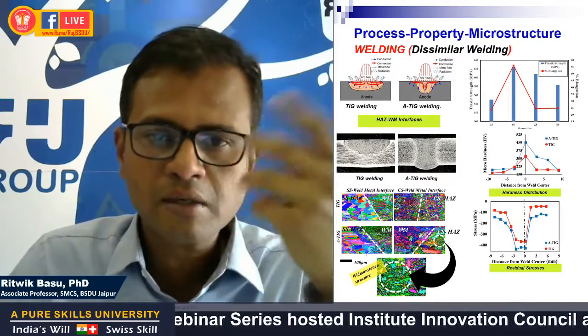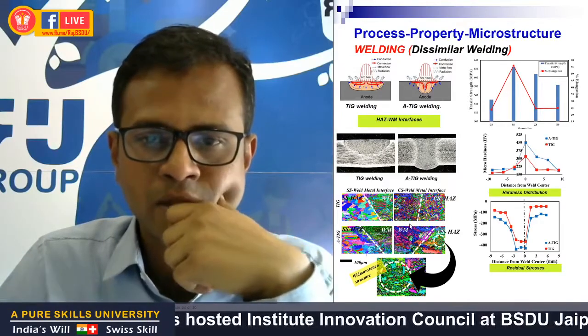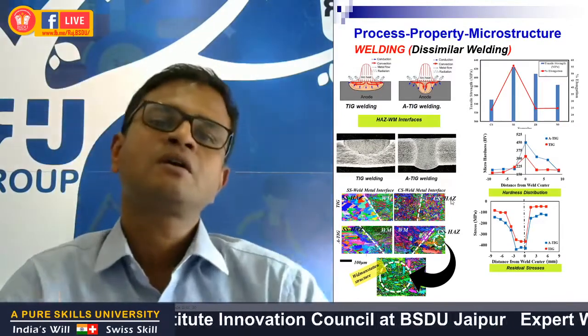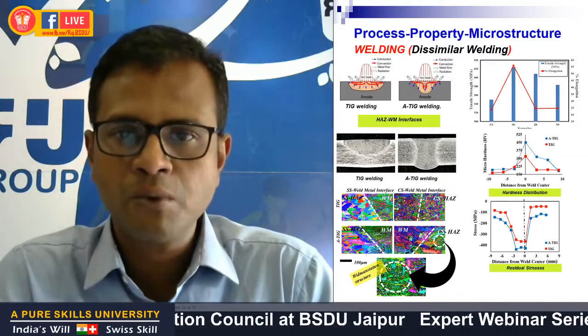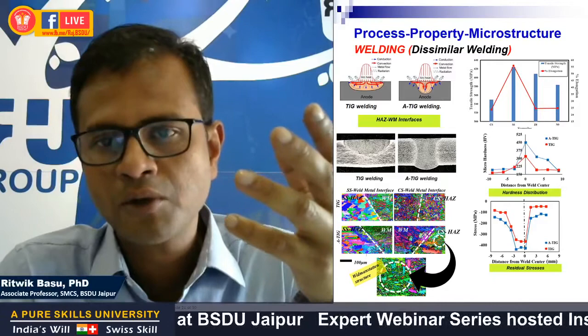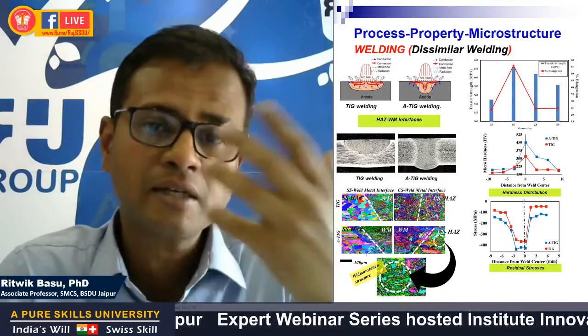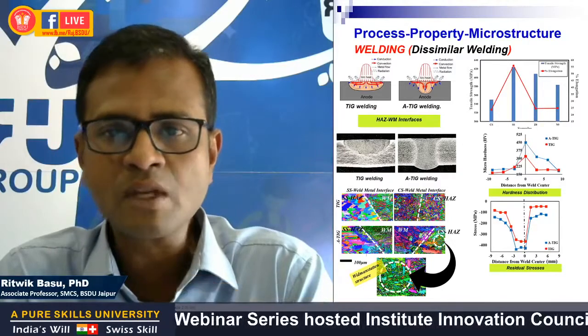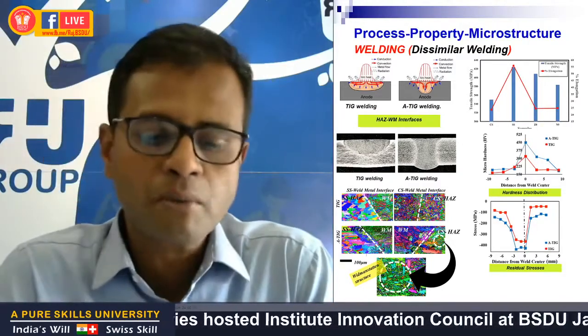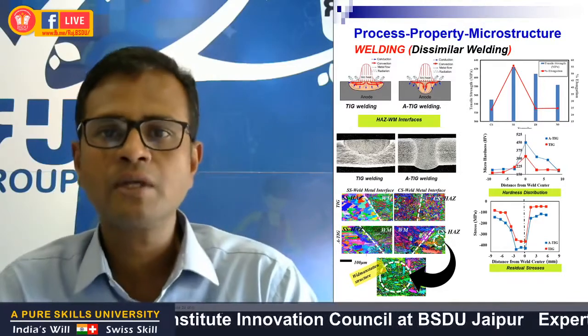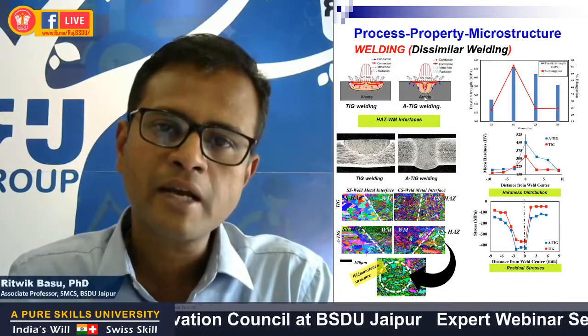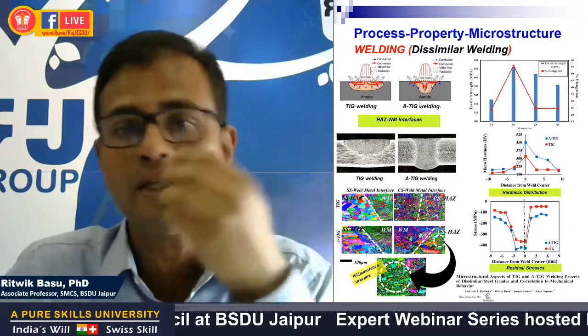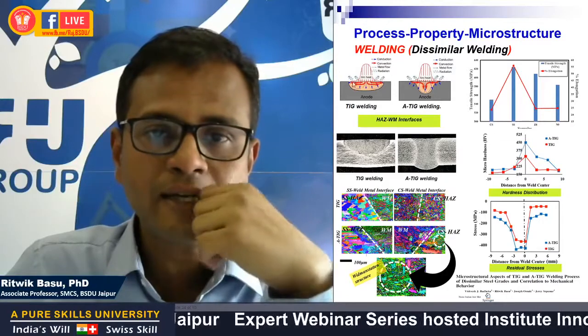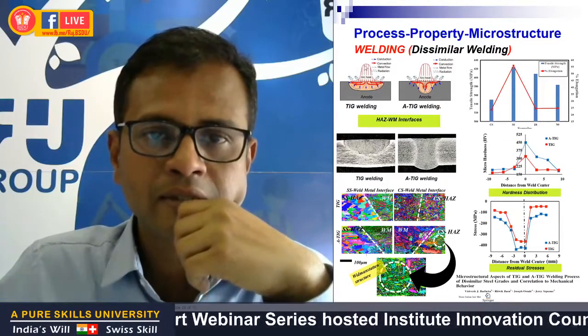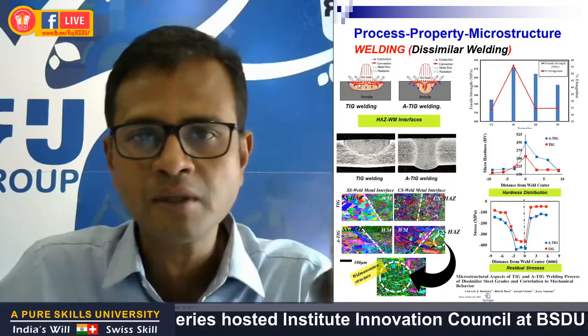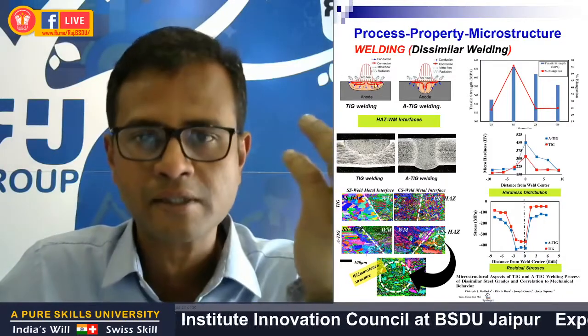So a difference as could be seen between the TIG and the A-TIG welded specimen could be because the heat affected zone underwent a two-phase transformation during cooling. A high temperature transformation from delta ferrite to gamma austenite, and then gamma austenite to alpha ferrite in the second state. Now during welding, when all other material properties are uniform, the cooling rate depends on the amount of molten metal available and also the availability of the heat sink to conduct the heat away from the melt. So in case of TIG welding, the weld pool is much shallower and the arc energy heats up the weld region and the surrounding region to a much higher extent.